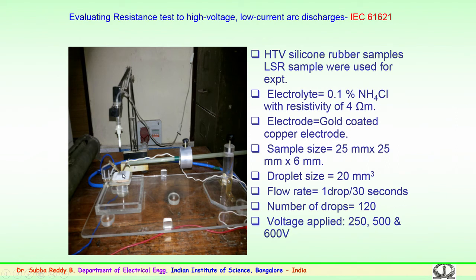is applied continuously over a period of time while the drops fall continuously at regular intervals. You can see that the HTV silicon rubber samples, or the sample which is kept here, could be of high temperature vulcanized silicon rubber or the liquid silicon rubber which is used for bushings. So, in the present case 2 types of samples were used for experimentation. The electrolyte or the contaminant consisted of 0.1% NH4Cl with resistivity of 4 ohm meter. Then the electrode, as mentioned, was gold coated copper electrodes, very important.